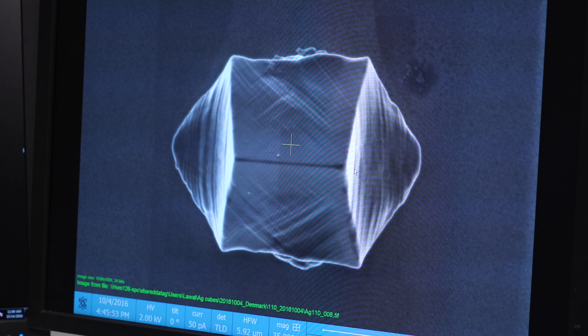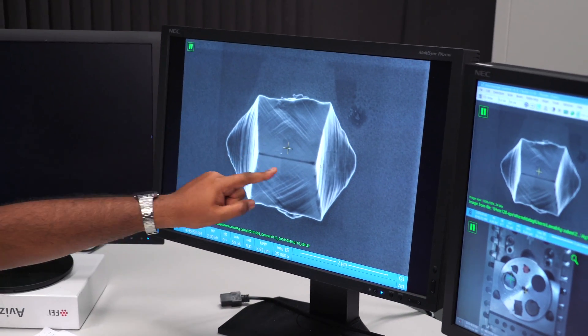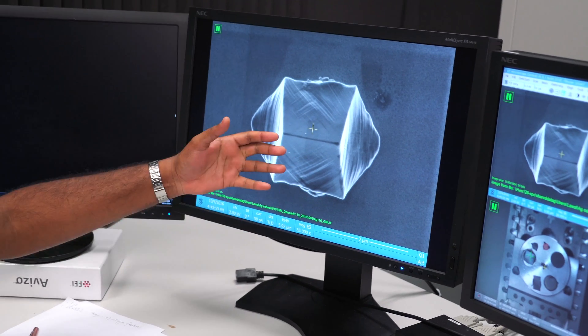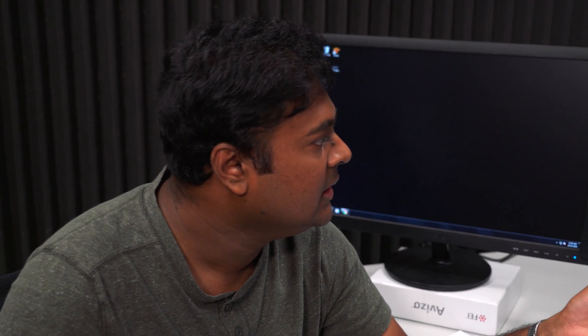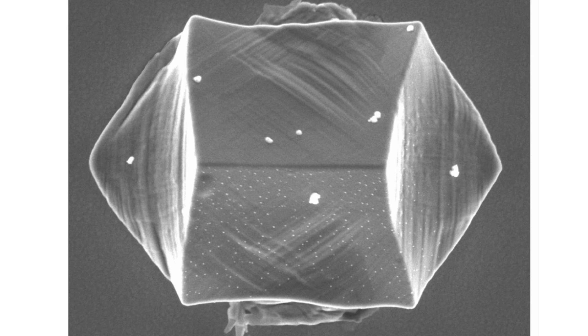This is a cube that was impacted in a 1-1-0 direction along an edge. You can see that this conforms to certain symmetry directions on the external side. And also you can see the slip systems that are characteristic of the intrinsic crystal structure. The crystal structure inside is a face-centered cubic structure, which leads to this kind of slip system forming, showing very interesting deformation.